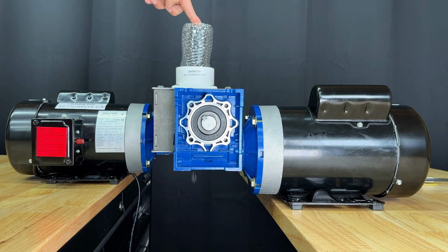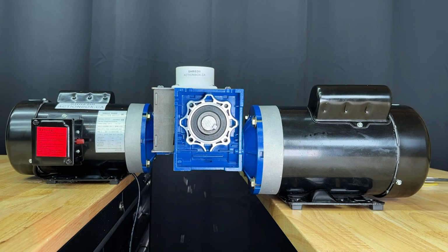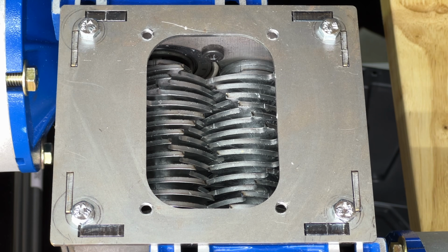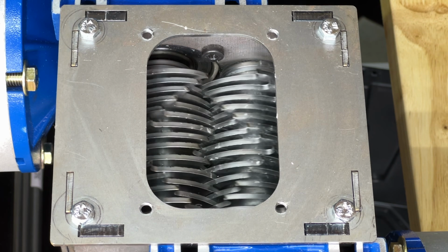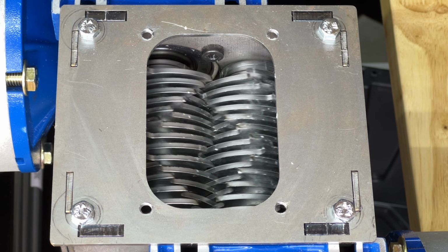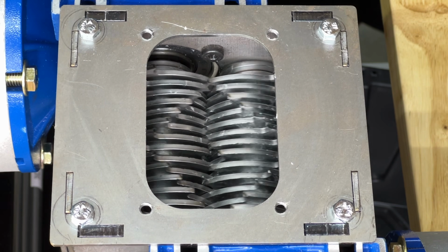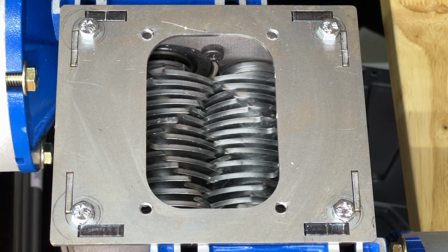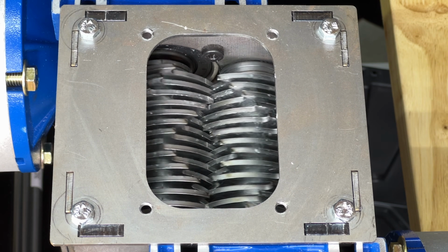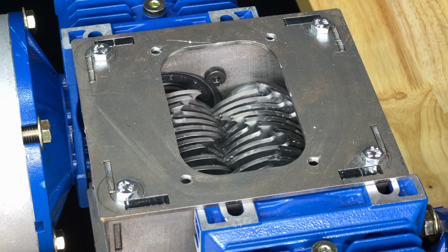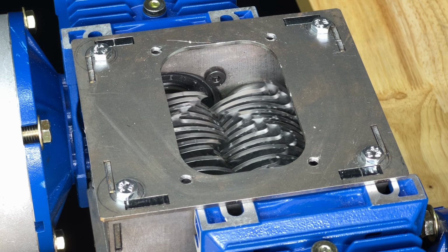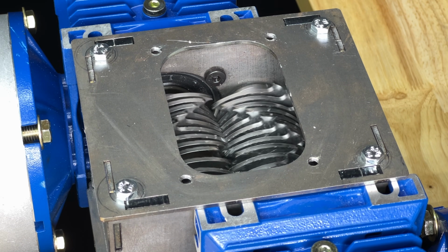Compared to my reclaimer, Shreddy not only has more blades, but each blade has larger and more aggressive teeth, which have no problem grabbing a hold of the thin wall plastic bottles. Dave and Alan's design includes 2 different sets of teeth, which are rotating by independent motors. Varying the RPM of each set of blades together or separately allows for different shearing or cutting profiles to be achieved. Higher shear is ideal for tougher materials, and lower shear for materials that tend to be over-granulated.